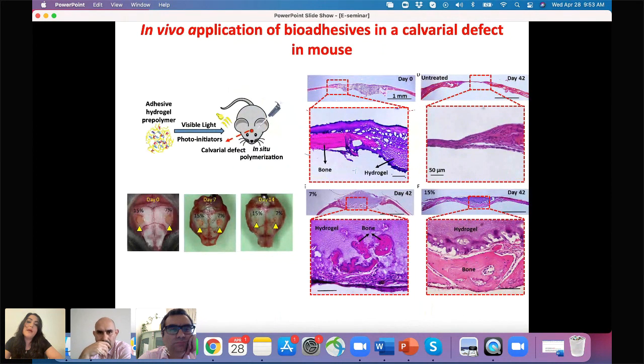We next performed an in vivo experiment using a calvarial defect model. This was done in Professor Intini's lab, where we created a calvarial defect in mice, and then we applied two different formulations of the hydrogel. One was formed by using 15% gel, and the second one was formed by using 7% gel. So I call them a stiffer and softer matrix. For 7%, the modulus was lower as compared to 15%. Our goal was to see what happened to bone regeneration when we implant different formulations of the hydrogel.